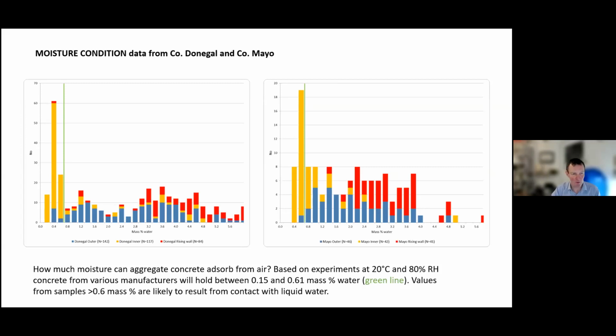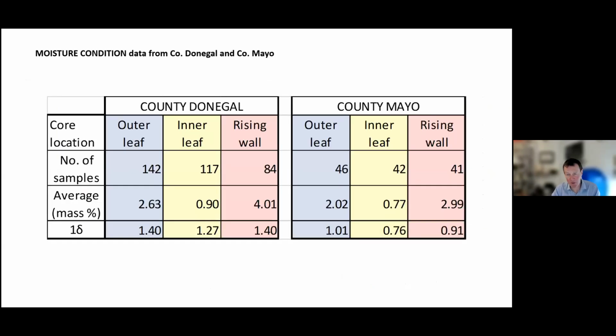And you can see that some of the concrete in Donegal, particularly if you look at the outer leaves, these are colored in blue, they're not just damp or wet, they're absolutely saturated. It's as though they're sitting in water. Same for Mayo, with a lot of water in the outer leaf, less so in the inner leaf. And well, the sub-DPC beneath ground level, that's expected to be wet. And here's the same data just shown numerically.